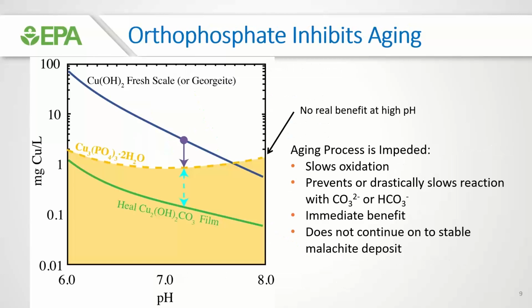Well, as we look at the aging model, going back to that, we start out with our fresh scale of georgite or cupric hydroxide. And as we add orthophosphate, we find an immediate benefit. This immediate benefit we'll illustrate by assuming that this particular solid forms, although again, it's generally amorphous and we really don't know what exactly the material is. But nonetheless, we do know, and very predictably so, that it has a much lower solubility than the cupric hydroxide.